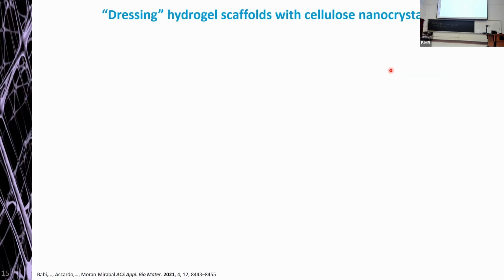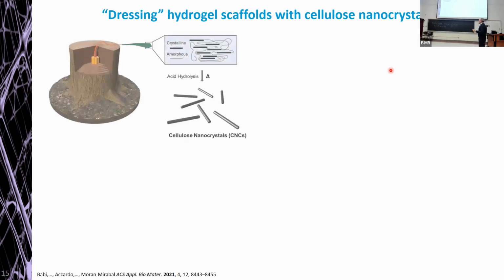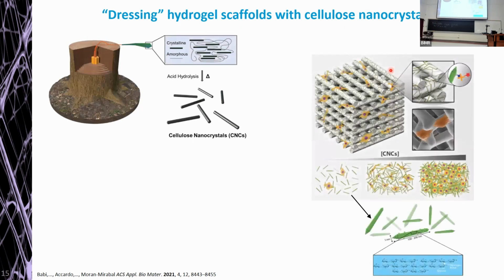And then I met Jose, and we started to wonder, okay, nice scaffolds, but let's functionalize them even further, maybe with a coating which is fully natural, like cellulose, and in particular, the very nice cellulose nanocrystals with which Jose is working. And Muhammad, we worked together in the lab, and we started to develop the polyethylene glycol diacrylate scaffolds, functionalized with different concentrations of CNC, of which you can see the typical dimension over here.